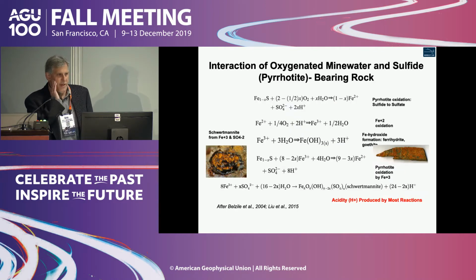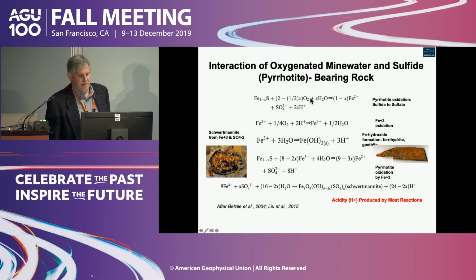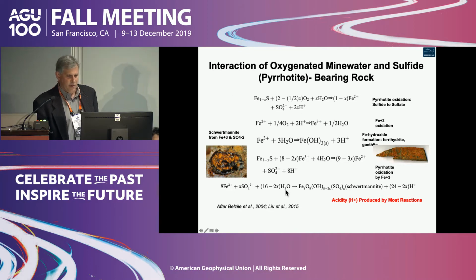So what are the things that we might expect to see in these cases? Well, there's a whole series of oxidation reactions, starting with, say, pyrrhotite oxidation, going from sulfide to sulfate. And basically, through all these reactions, most of them generate a lot of hydrogen ions, so decreasing pH. And going through pyrrhotite oxidation, then we can form things like ferrihydrite, goethite, so forth, iron hydroxides. And then finally, with Fe3+ and sulfate, we can form some of these kind of odd mine minerals like schwertmannite and so forth. So these oxysulfates, hydroxides. So these are the kind of reactions we have driving these pH changes.